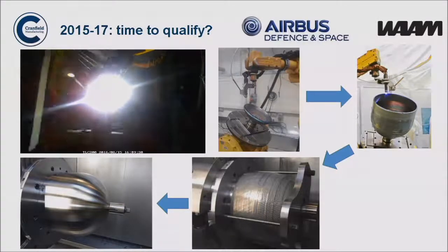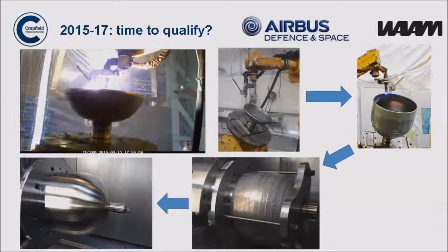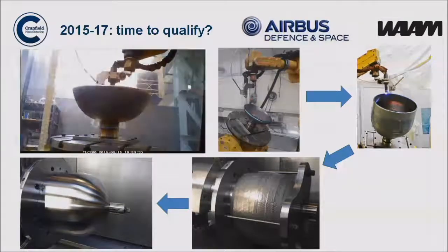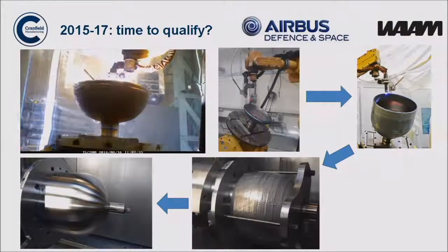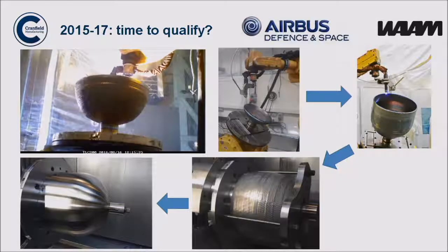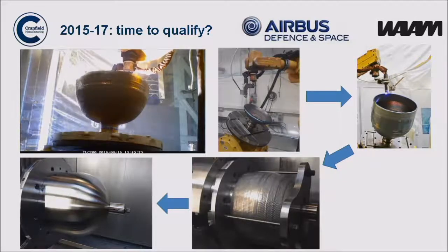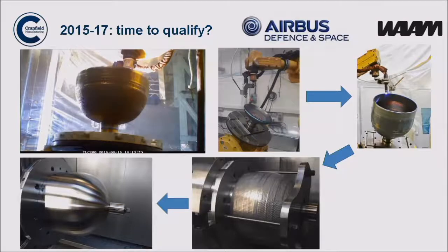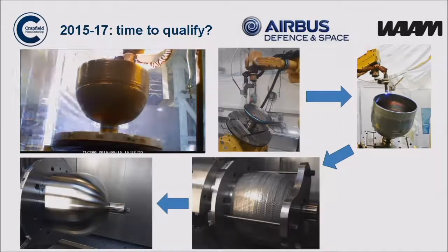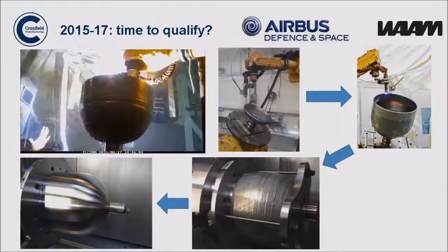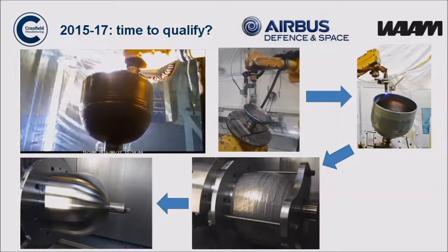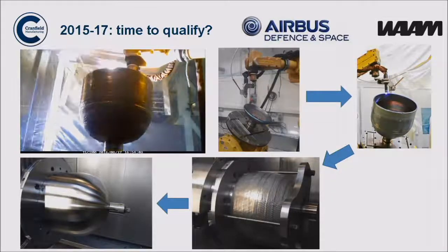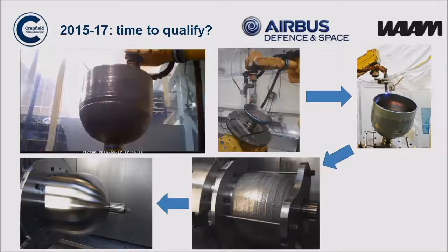I'll just let the video run a bit more so you can see the final part being built. You can see we're continuously rotating the part and changing the build direction as we're doing this. We're also changing the build strategy to deal with different thickness of material that we're putting down. And of course, when we get to the end, we also rotate it round and put the flanges on. You can also see that we're building in a tent, so we don't use a full fixed enclosure. We tend to use this tent for this size of parts.